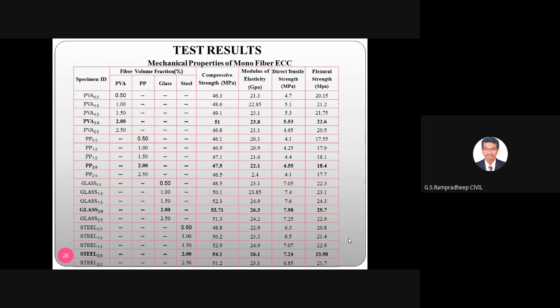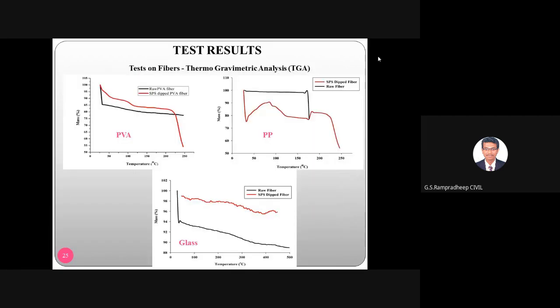See, you can now assume that the high modulus fibers are glass and steel, and the low modulus fibers are PVA and PP. In low modulus, PVA shows the better result, and in high modulus, glass and steel are almost the same. There is around 0.5 Newton per mm square difference, right? You just compare the E value also, then direct tensile strength, and even the flexural strength, right? So just compare the glass flexural strength with the steel flexural strength for 2% volume fraction. Even though the compressive strength for glass is 53.71 and for steel it is 54, a slight increase in steel, for tensile and flexural strength, bending resistance is better for glass than steel because of the density, as we have already seen here, right?